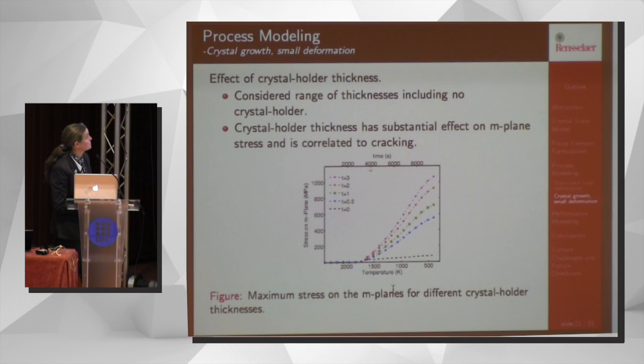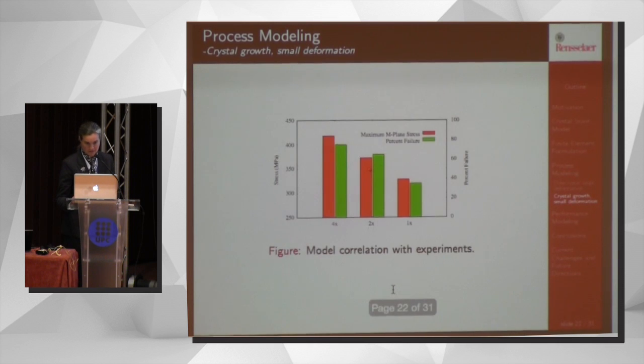The crystal holder thickness, we found, had a big impact, and by thinning it down, you could greatly reduce the stresses that lead to cracking. And in fact, they did experiments then at Crystal IS where they varied the crystal holder thickness, and we see that as it goes down, from 4 times to 2 times to 1 times the original size, the stress on the M planes correlates very strongly with the percent of failure that they were seeing.